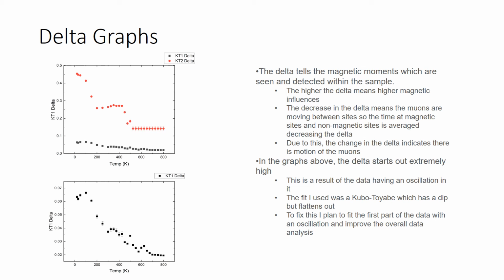And then it starts to decrease, and this is a result of the data having an oscillation in it. As you can see, it seems like it's almost oscillating here, which is a result of the data itself, the asymmetry versus time graph, actually having an oscillation in it. Whereas a Kubo-Toyabe, the fit which I used, doesn't oscillate. It has an initial dip, and then it flattens out. Whereas the data itself seemed to almost have a damped oscillation, where it got smaller like this.